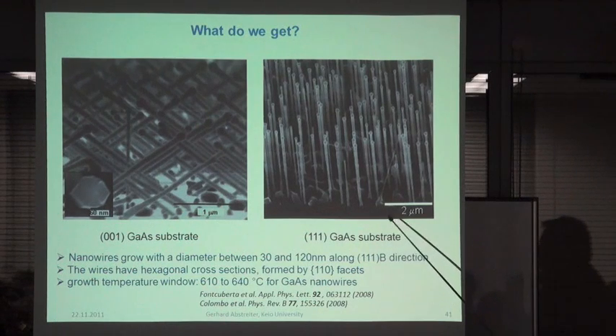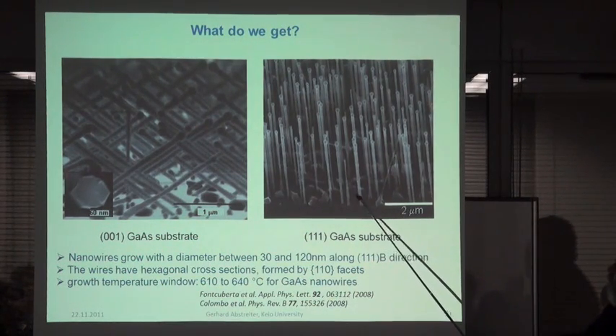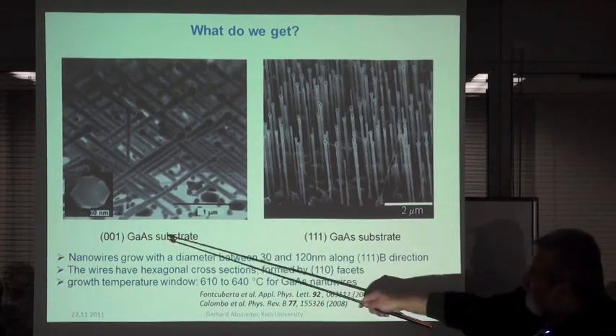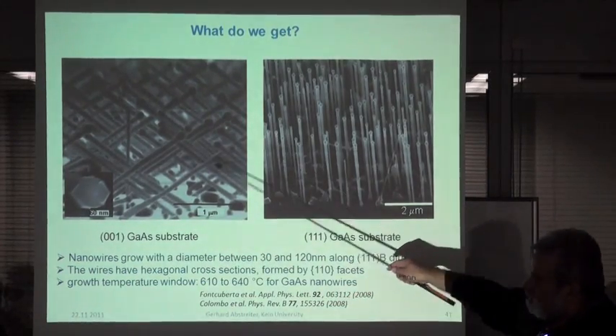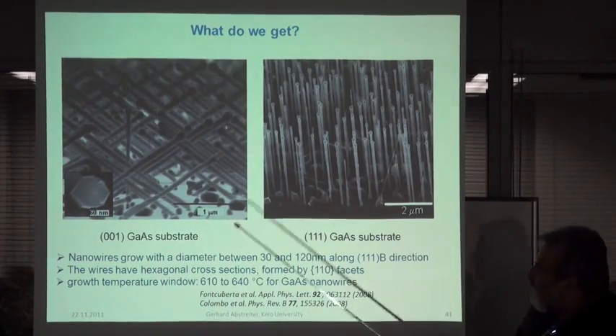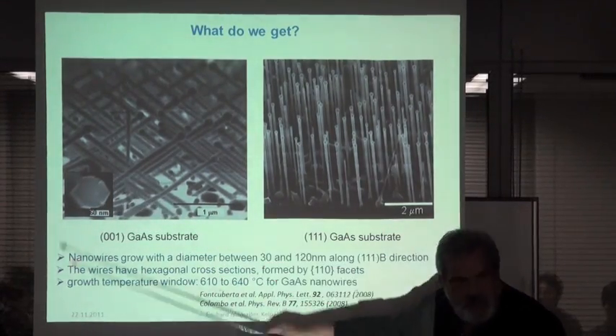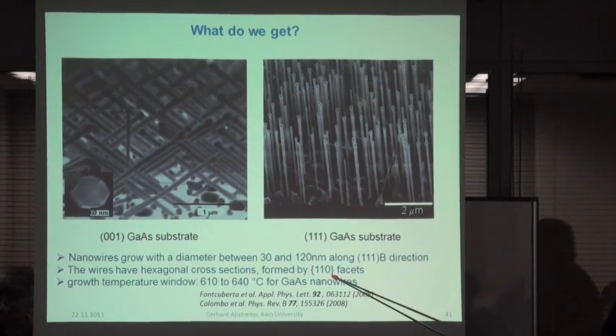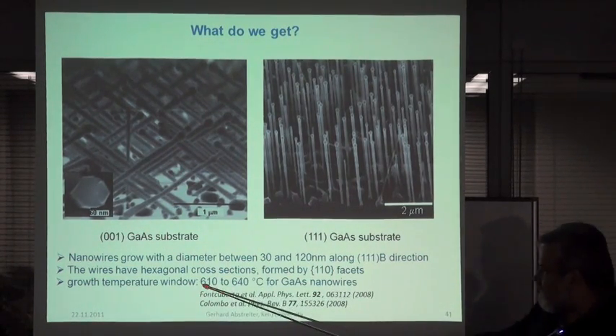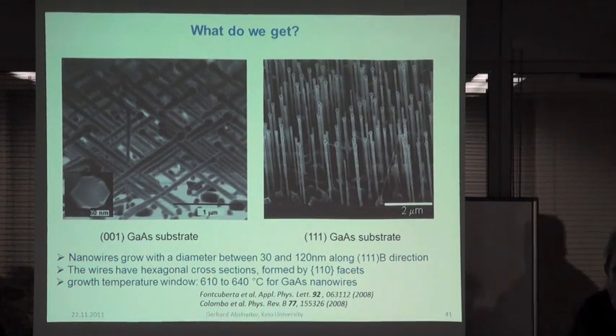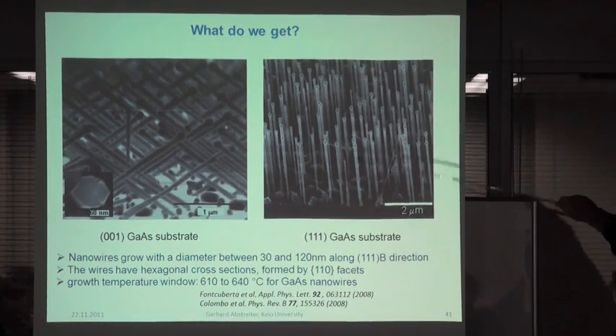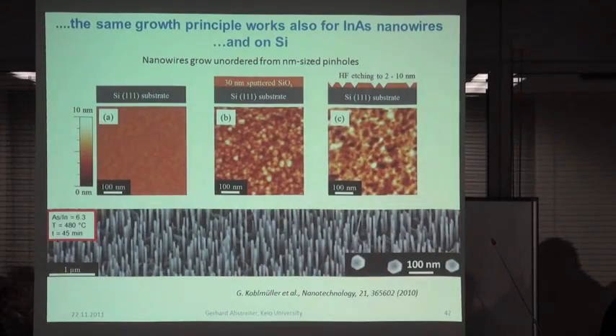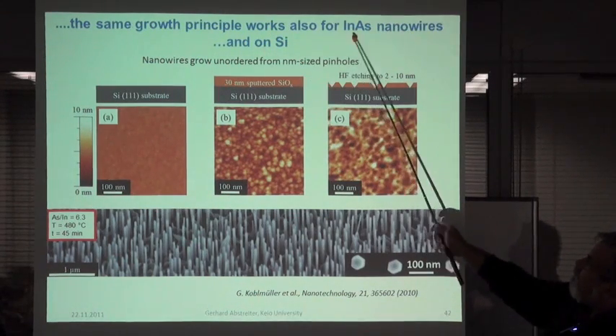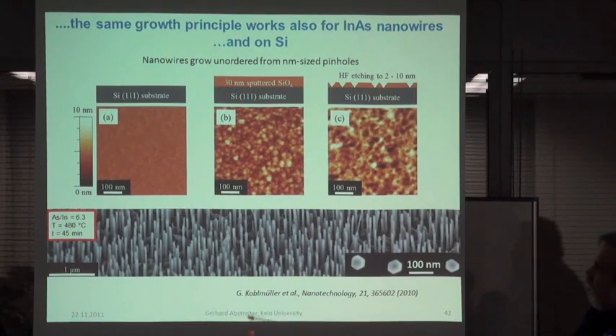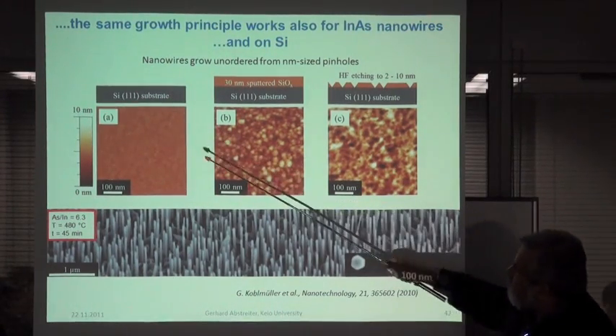And these were our first results about 3 or 4 years ago on gallium arsenide. And you see immediately that we have epitaxial relation. They grow along the 111B direction. When I take a 001 substrate, they are tilted because they want to grow in a different direction. They have a hexagonal shape here, which is formed by 110 facets. And for gallium arsenide, we have a limited growth rate, at a certain temperature where we can grow this. So they grow vertical here. So this, I think, was the very first samples which we have grown about 4 years ago now. The same growth principle works also for indium arsenide and also on silicon. So this is this thin oxide on silicon 111.